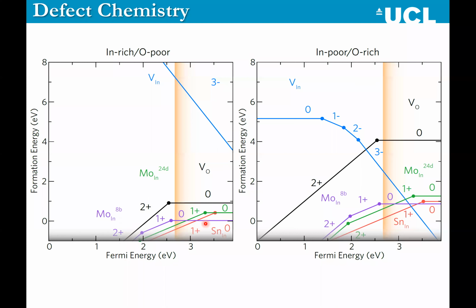Tin, shown in red, is a very low energy dopant, and it injects electrons directly into the conduction band. And molybdenum on the 24d site, so this is the irregular shaped octahedron, is also a low energy defect and it injects electrons directly into the conduction band. What changes is the molybdenum on the 8b site shows a very different behavior. Its transition from the +1 charge state to the neutral charge state occurs below the conduction band minimum, meaning that electrons would have to be excited into the conduction band for this defect. So you have two different defect behaviors going on depending on if molybdenum goes on the 8b site or the 24d site.